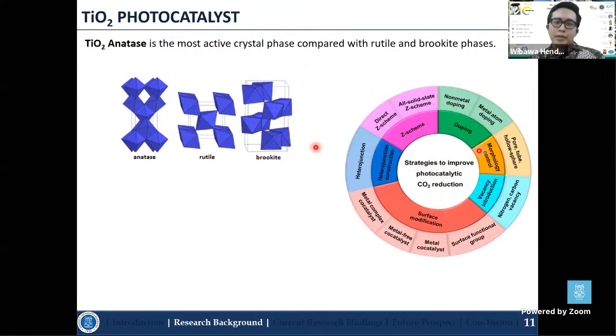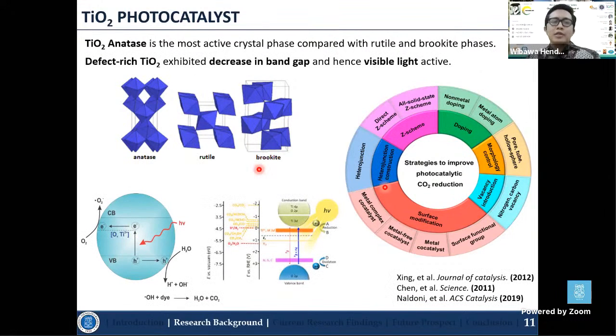So therefore, several strategies have been developed in order to increase the photocatalytic efficiency of titanium dioxide, such as doping with the metals or non-metals, surface modifications, Z-scheme heterojunctions, and also the defect generations. So my research is actually emphasized on creating the defect on the titanium dioxide, since the defects can actually decrease the band gap and hence make the titanium dioxide become visible light active.